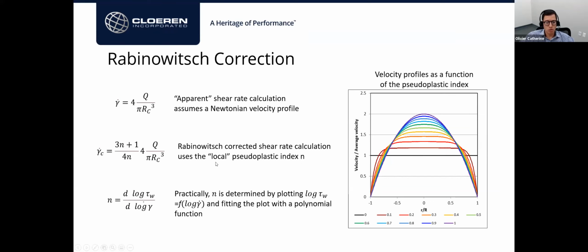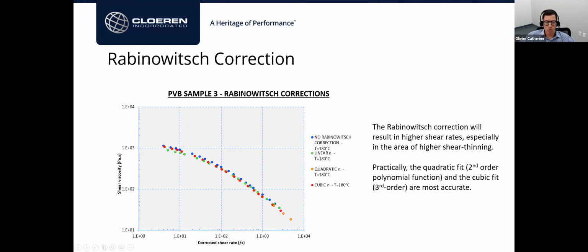And practically, how do you do that? You calculate the n value with a polynomial fit of the log of the wall shear stress as a function of the log of the apparent shear rate. You fit this and you're able to determine the n value. Of course, there are different ways to fit that. You can do linear fits or a higher degree polynomial fit. So this is what I'm showing here.